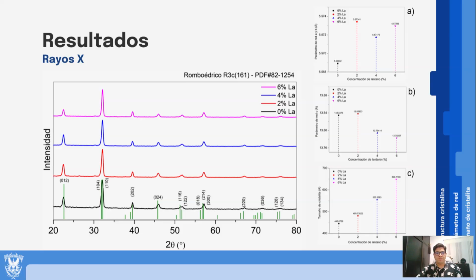Notably, lanthanum doping induced anisotropic lattice distortions. The a and b axes expanded, while the c axis contracted. Additionally, the crystallite size increased progressively with lanthanum concentration. These changes were attributed to the smaller effective ionic radius of lanthanum in 12 coordination sites, modifying the unit cell volume. The study successfully correlated doping-induced structural changes with lattice parameter evolution.